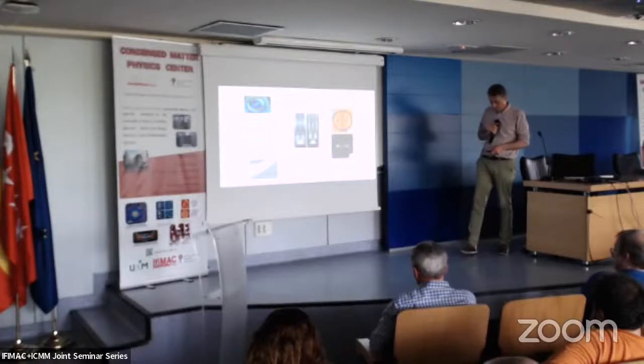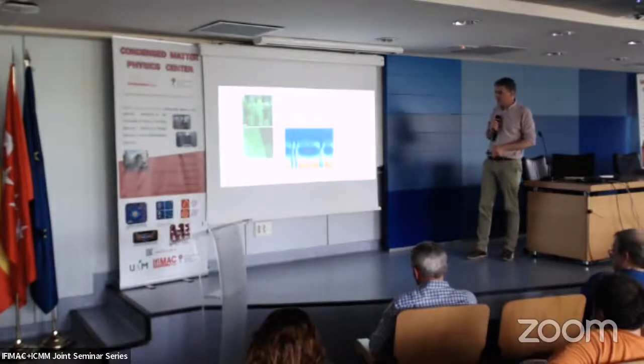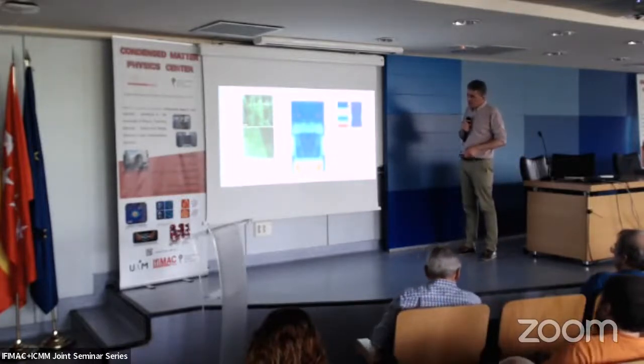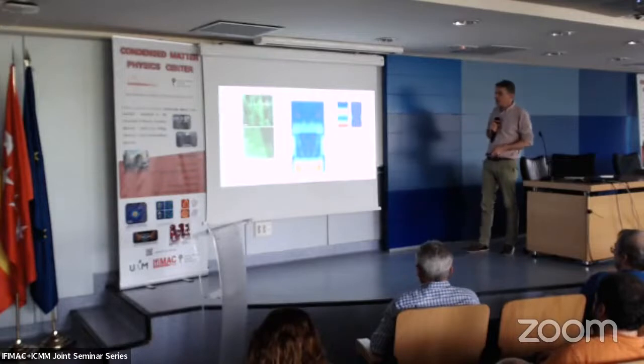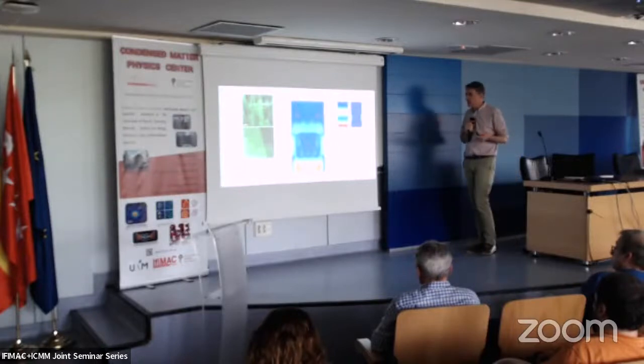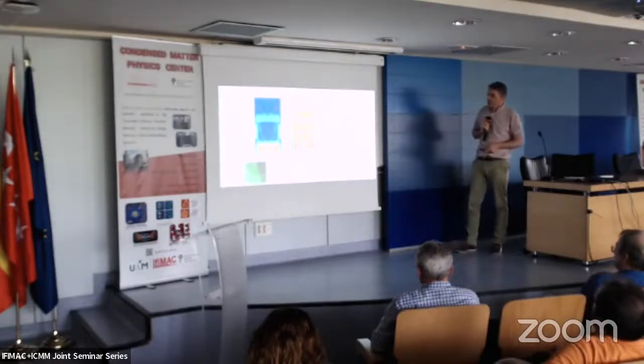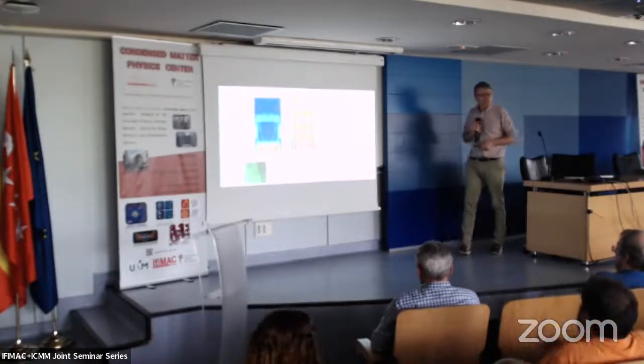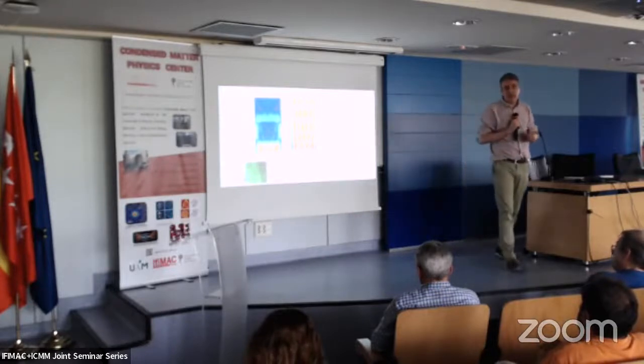However, in that case, the width would be very large. This is hundreds of millivolts. So instead here we have something which is just a fraction of a millivolt, and you are going to see this in more detail. For example, here we take one particular terrace, and we have here 4 states, 5, 6, 7, etc., and we have the level separation which is obtained here. By removing the background, which is due to all the anomalies which happen in the bulk, we can obtain the level quantization. So we really see that we have quantized levels, and what is very peculiar here is that the dispersion relation of these quantized levels corresponds to 17 times the free electron mass. So we have very heavy, heavily correlated electrons, which provide us our quantum levels.